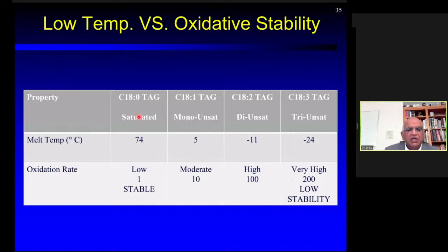If we take the saturated tristearin, it melts at 74 degrees. It is a solid, having flow properties of nil. However, if we go to the trilinolenin, its flow properties are excellent. However, the tristearin has excellent oxidative stability, because it is a saturated material, but this unsaturated material has very low stability, whereas these mono and diunsaturated materials have intermediate properties.